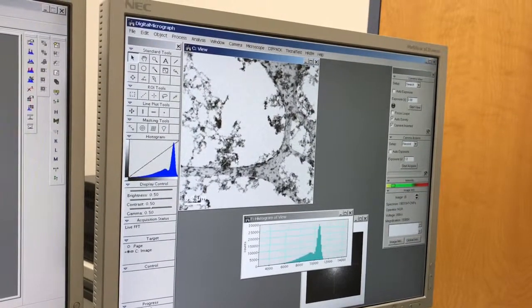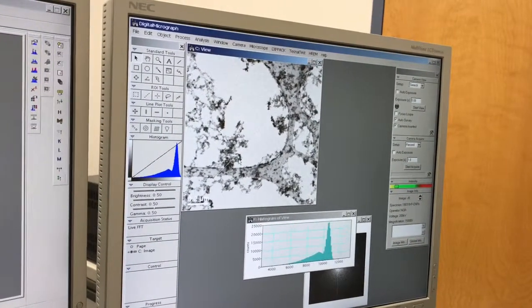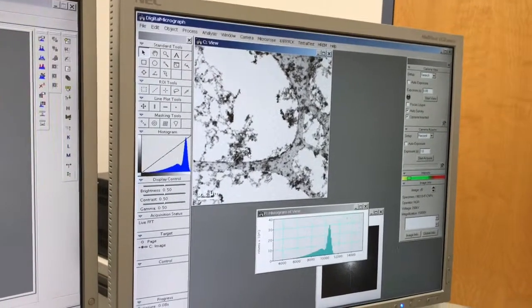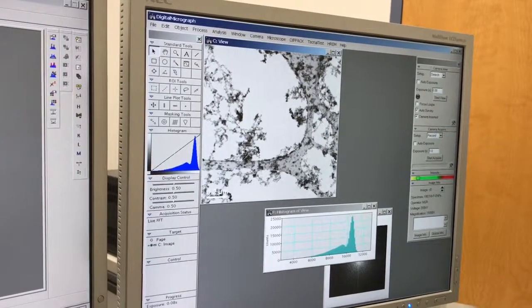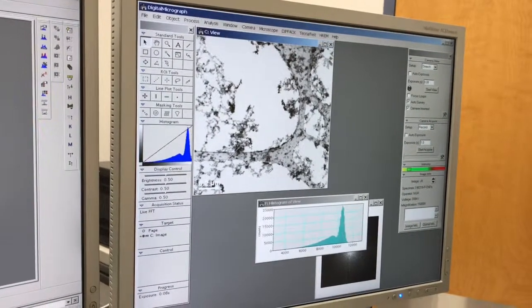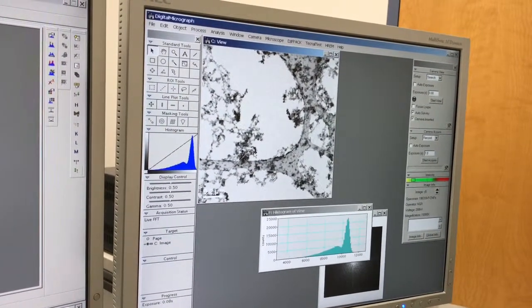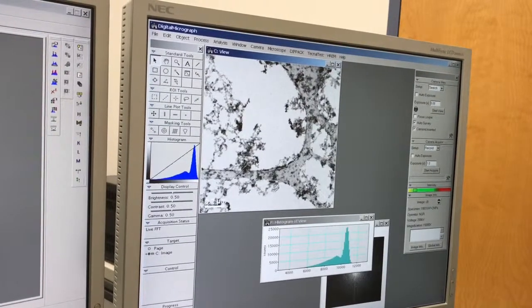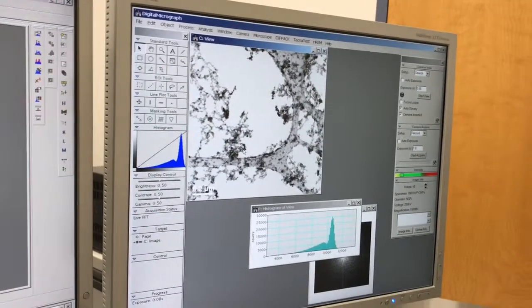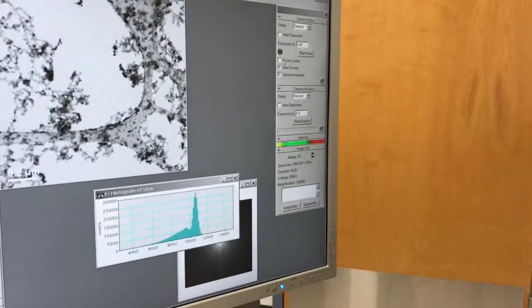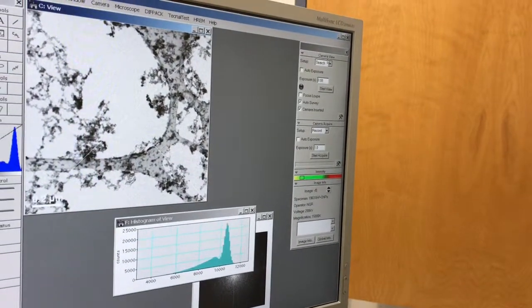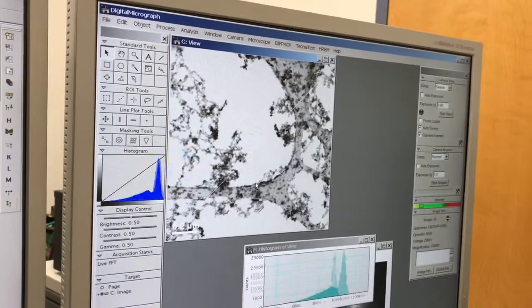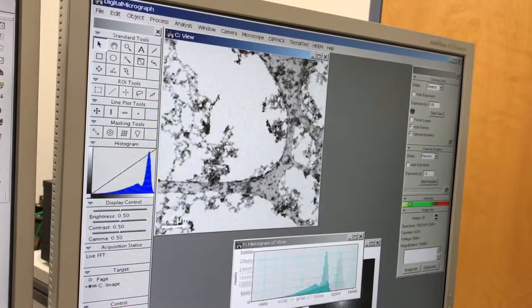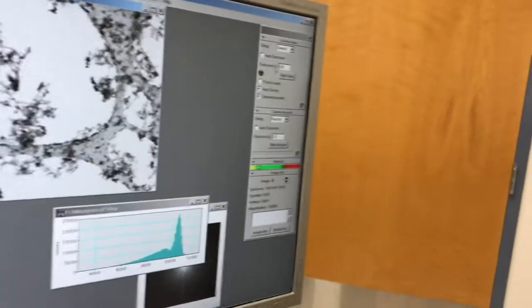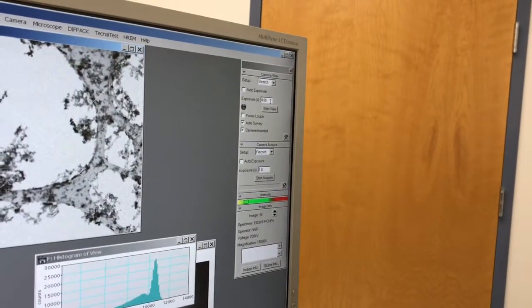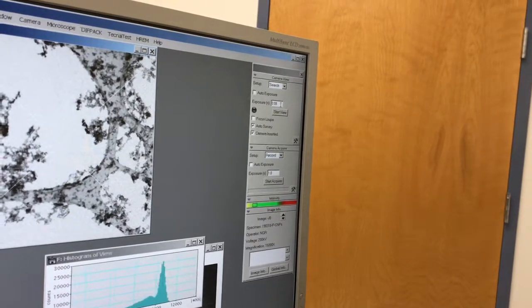As a result of that, I end up with approximately 16 times more effective pixels in the acquired image than the view. So that translates, in terms of the exposure time, I have an exposure time here in acquire and view. If I want to get counts in the acquire that are similar to what I get here, I have to multiply this number by 16 theoretically.